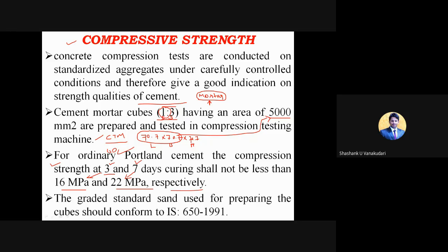After preparing the mold, we need to place it in the water bath for the curing process. After curing for several days, like 3 days and 7 days, the strength should be more than the given value. For 3 days of curing, it should be more than 16 MPa, and for 7 days of curing, it should be more than 22 MPa.